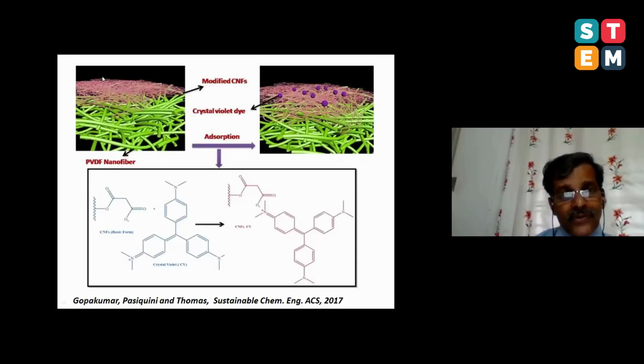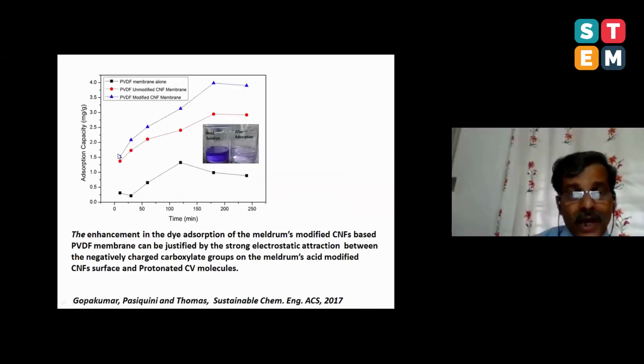Look at this, this is the commercial filter coated with nanocellulose, the top, which is shown, is a violet color. This is after separation. You can see all the dye molecules have been retained by this filter. This is PVDF. And when you do a chemical modification of nanocellulose, you are introducing COO minus group. And this COO minus group can interact with the crystal violet dye by electrostatic interaction. Therefore, we could catch all these dyes very effectively. That is why, look at the separation efficiency. The chemically modified nanocellulose was very efficient. Look at this, this is the impure water, this is the pure water.